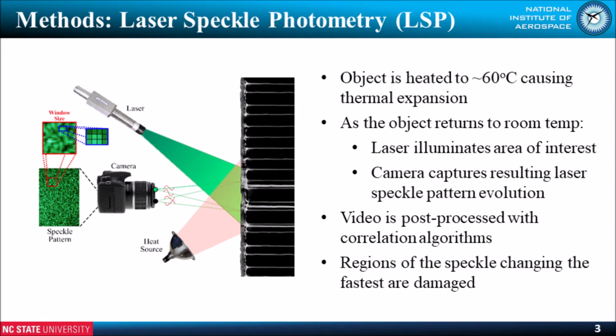Typically, when a laser illuminates a microscopically rough surface, which includes most surfaces aside from mirrors, the roughness causes the laser to randomly scatter, forming a laser speckle pattern. An example can be seen on the far left. This pattern normally remains static, but as the thermal expansion reverses and the composite contracts, the roughness also contracts. You can imagine the roughness as many very small peaks and valleys being stretched and squished as the composite is heated then cooled. As these peaks and valleys contract, the laser light scatters in a new way, causing the laser